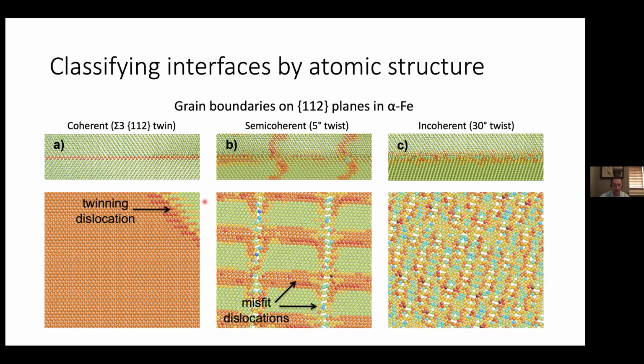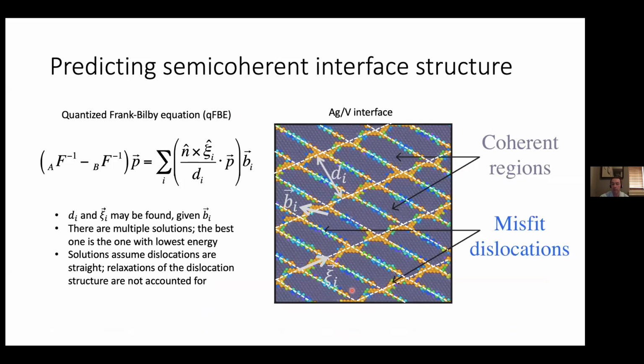So a lot of work has gone into studying all of these different boundary types, but I wanted to give you just a little bit of a vignette, a little introduction into work that we've done studying semicoherent interfaces of the type that I'm showing you here in the middle. So in other words, these are interfaces where the crystallographic character allows for the structure to develop into a series of coherent patches separated by misfit dislocations. Here's an example of the internal structure of a silver vanadium heterophase interface. So again, just like with the alpha iron boundary that I was showing you a moment ago, this one can be viewed as consisting of coherent regions separated by misfit dislocations.